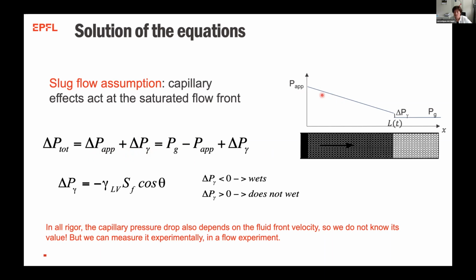So that's the delta P total, and my delta P applied is the pressure that I have here minus the pressure here plus this delta P gamma. So if delta P gamma is negative, in fact, the pressure will be below. So I have a negative pressure that sucks, if you want, the fluid in there. And if my delta P gamma is positive, then it means that it does not wet, and I have to overcome this capillary pressure to force the fluid to penetrate into the porous medium.